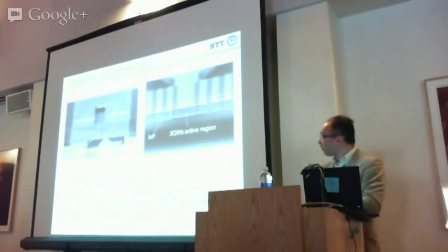This is the IV characteristics of the room temperature continuous-wave operation of the device. This shows the behavior close to the threshold. We can achieve a threshold current of 7.8 microamperes. This is a record value of room temperature continuous-wave operation for any type of laser. And the red line shows the voltage curve. And this is a wide range L-I curve, IV curve, and wall-plug efficiency. First, after the threshold, the wall-plug efficiency is about 6%. However, it dramatically decreased. We think that this is due to the leakage current through the substrate.